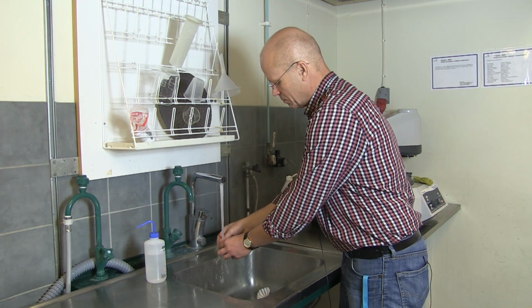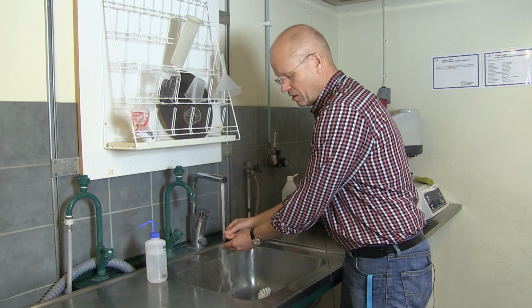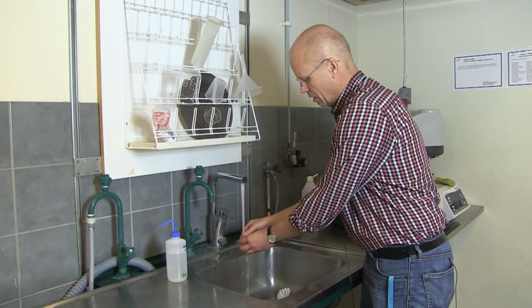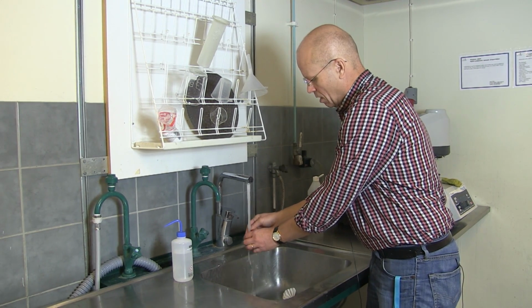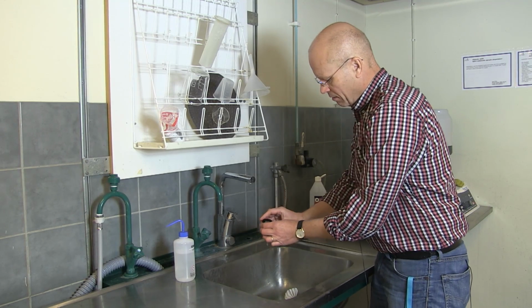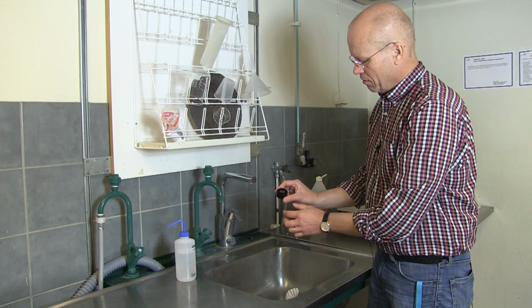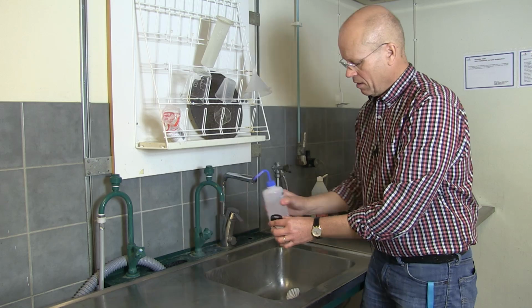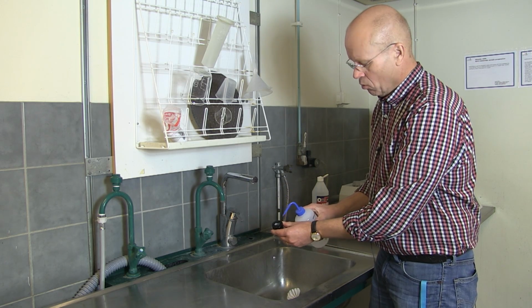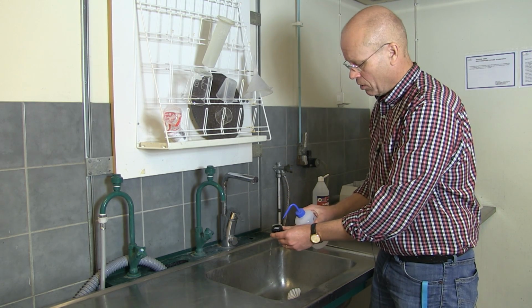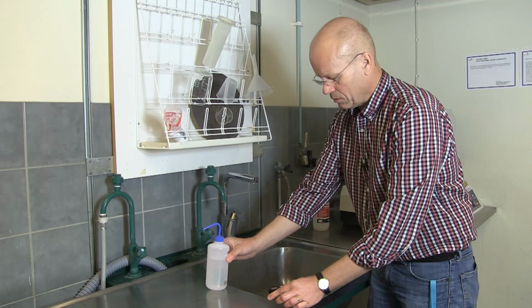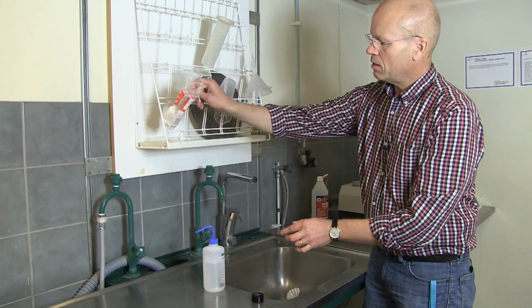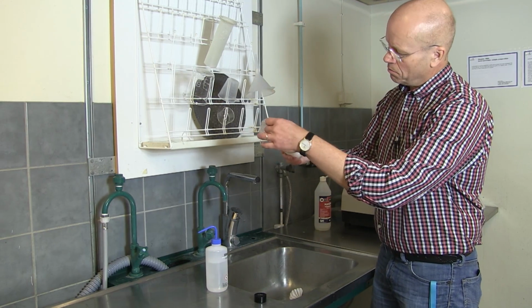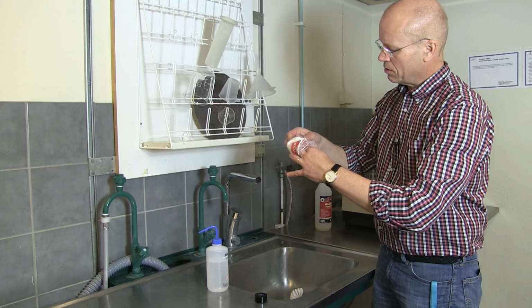Water. Soap is not necessary after final polishing. It's enough with water. But water is very active on a freshly polished surface, so ethanol is a must to remove the water from here. Otherwise the sample will corrode, at least if it's a steel sample. It might be good also to take one of these cotton pads to clean the sample.